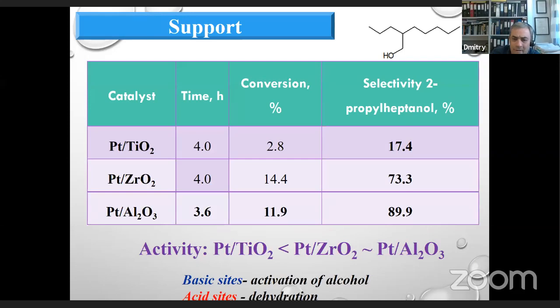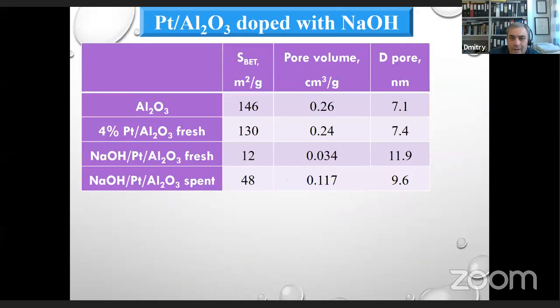Coming back to the influence of the support. Here we see the results for 3 catalysts on different supports. Alumina is more acidic, and as we can see here, selectivity to the desired product, to propyl heptanol, was higher on alumina, which we attributed to the involvement of acid sites of alumina, which is known to be a Lewis acid, in the dehydration steps. So once again, the catalytic system here is platinum on a certain support. Alumina turned out to be quite efficient, doped with dry, solid sodium hydroxide.